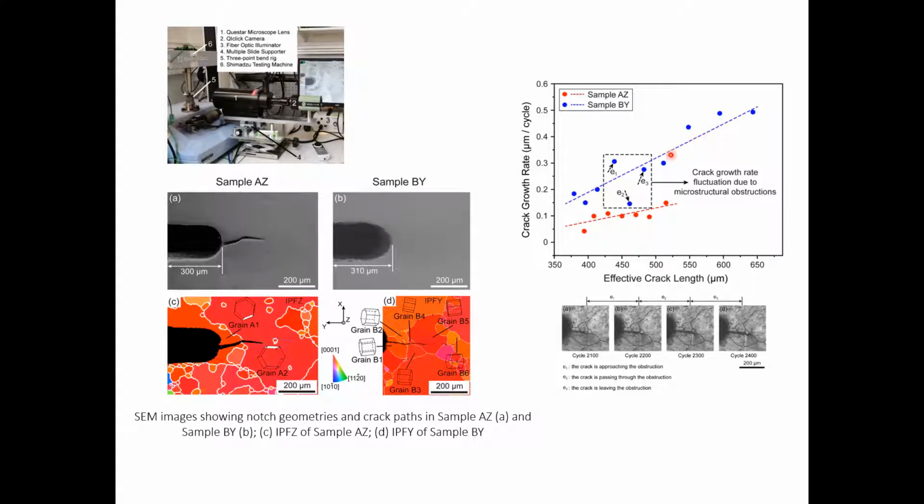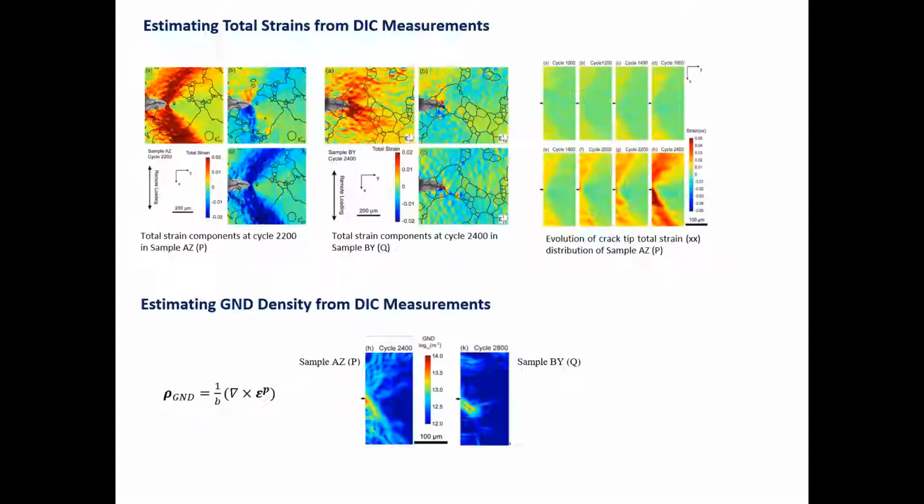direction, is considerably higher. And we also have this very interesting region around here where we see these variations in the growth rate, and that corresponds to this region in here where the crack is growing through interesting regions of microstructure, that is, crossing a grain boundary, coming pretty close to a triple junction, and then crossing another boundary, and then heading through another grain pretty uniformly of given crystallographic orientation. And so there's a variation in rate there. There are also fluctuations in here, but these are things we're really interested in trying to understand, and are very much the subject of ongoing current research. But nonetheless, clear-cut differences in rate from these differing crystallographic orientations.